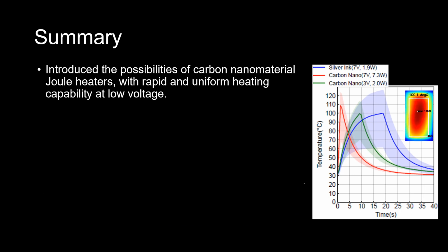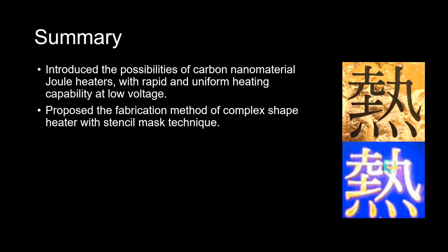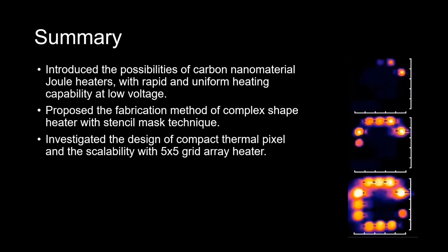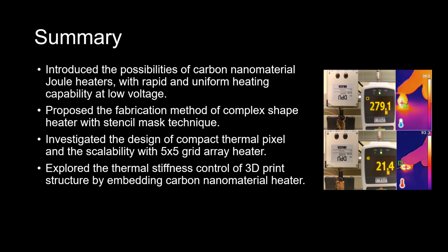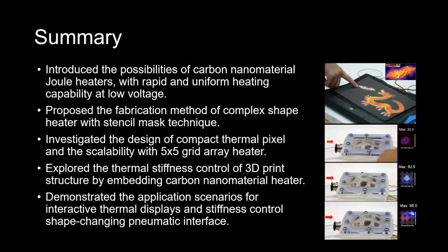In summary, we introduced the possibility of carbon nanomaterial joule heater with rapid and uniform heating capability at low voltage. We propose a fabrication method of complex shape heater with stencil mask technique. We investigated the design of compact thermal pixel and the scalability with 5x5 grid array heater. We explored the thermal stiffness control of 3D printed structure with built-in carbon nanomaterial heater. We also demonstrated the application scenario for interactive thermal displays and stiffness control shape-changing pneumatic interface.